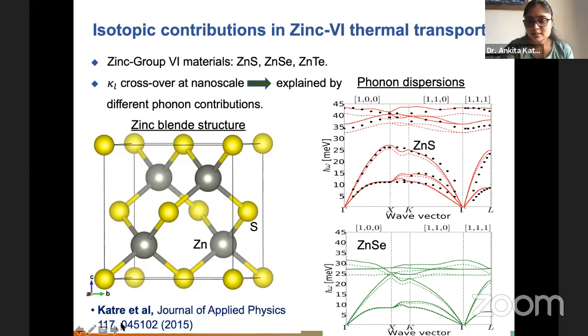So here now, coming back to the actual thing of the phonon dispersion. For the zinc sulfide case, we see that it matches well with the experiments. And the interesting feature is a big gap between the acoustic and the optical phonon frequencies. For those who don't know about these optical and acoustic modes, these three modes down here are basically acoustic modes, that is, the vibration of the whole crystal in 3 axes, and then all the upper frequencies are called optical phonon modes.